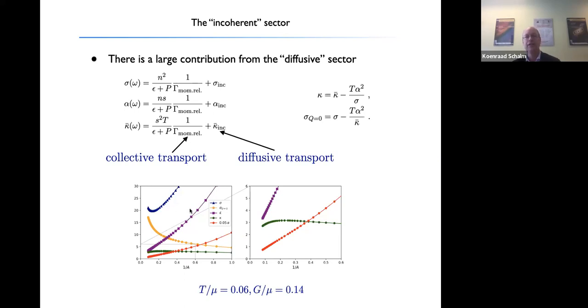And here you see it in relative terms expressed as a function of 1 over A, so large A is now to the left and small A is to the right. You see this is the full conductivity, and this yellow one is the conductivity at Q equals 0. And you see they start to approach each other. The same happens for the thermal conductivity kappa without electrical current, that's this green part, and the full thermoelectric conductivity bar kappa, which is this purple part. They start to become equal at very small lattice strength of the order of A is 10th.